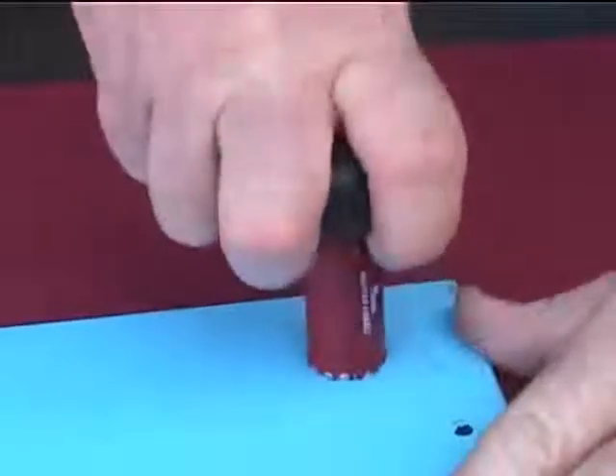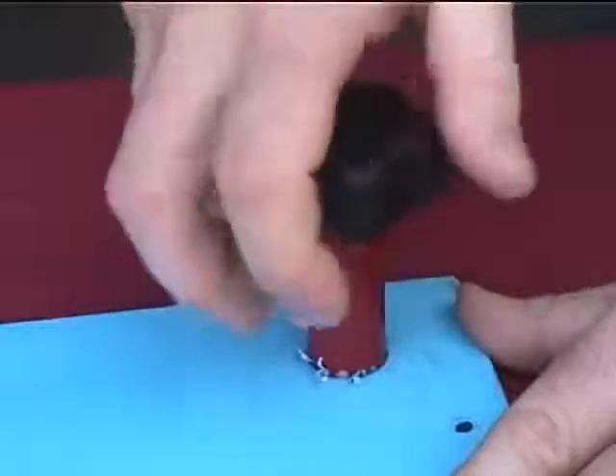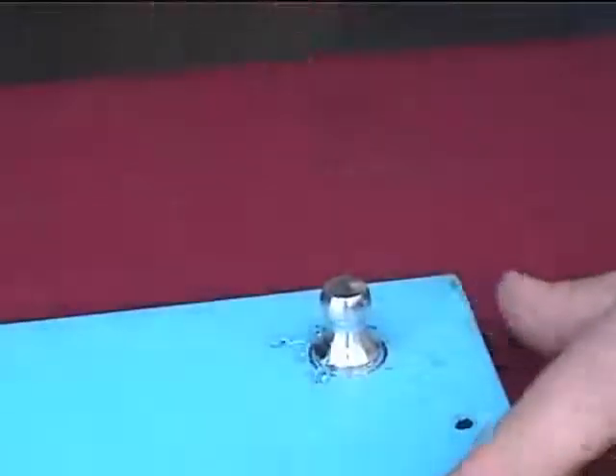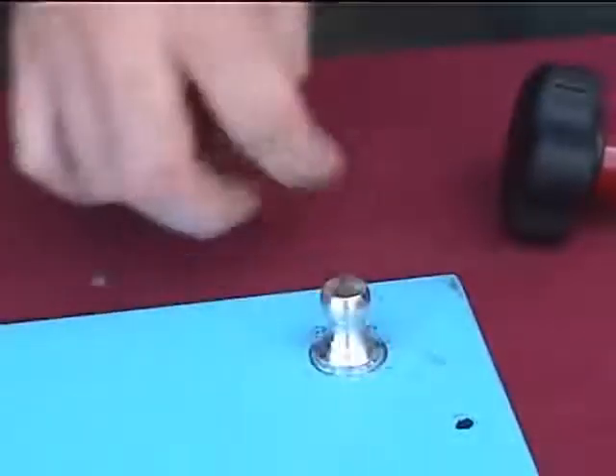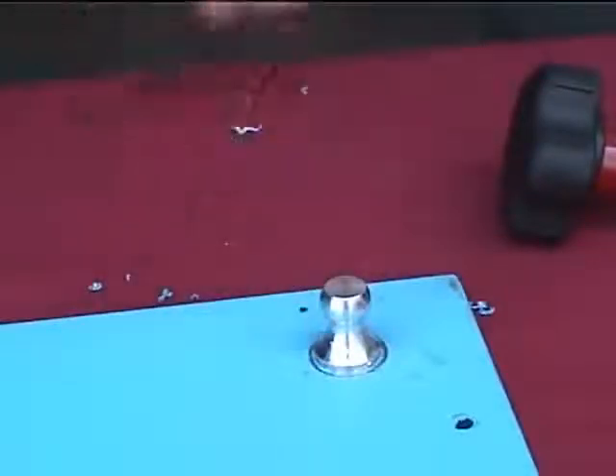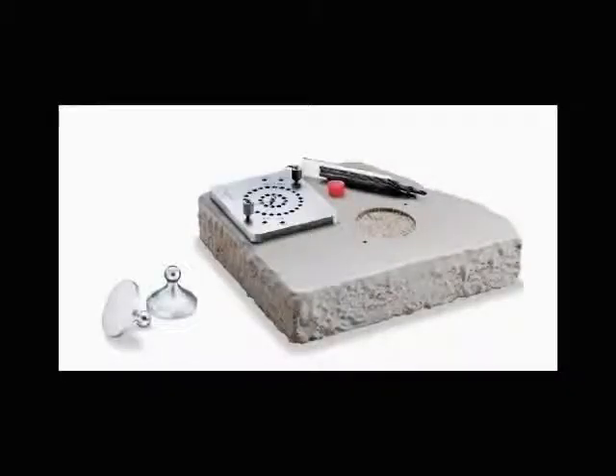When deemed necessary to cut through a coating to relieve unwanted lateral bonding stresses, the method utilized should minimize the induction of surface flaws such as microcracking. Such flaws may lower test results and create fracturing, resulting in partial pull-off results. For testing thick coatings with a 50 mm dolly, an optional drilling template may be preferred to a cutting tool.